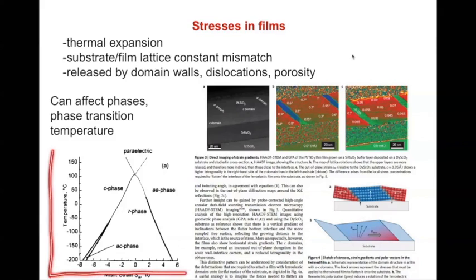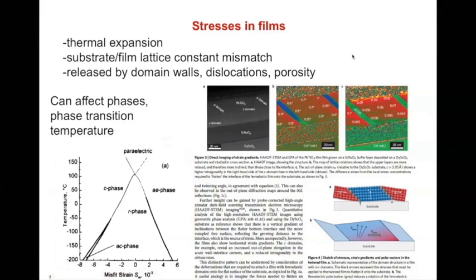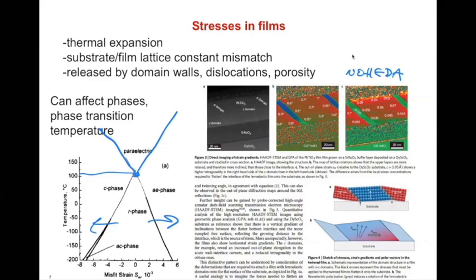Those strains can be strong enough to even shift the Curie temperature of a ferroelectric material by a very large amount. This has been illustrated using phenomenological theory by Sasha Tagantsev, and here in slides by Beatriz Noheda in Nature Materials. In the phase diagram of barium titanate, at zero stress the phase transition is around 120 to 130 degrees, but with large stresses the Curie temperature can increase by hundreds of degrees, and in some cases you can even induce new phases by these stresses.